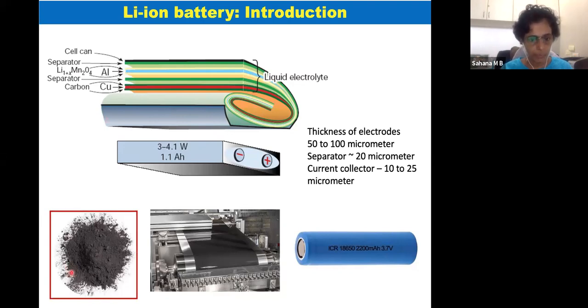Now I told you this is the powder. We coat it over this aluminum foil over here. The active material, along with carbon black and binder, is coated over both the sides of this aluminum foil. Both means front and back. That corresponds to this one here. The yellow line here corresponds to the cathode materials that are coated on the current collector, both the sides. And the green lines correspond to the anode material that is coated over copper on both the sides.